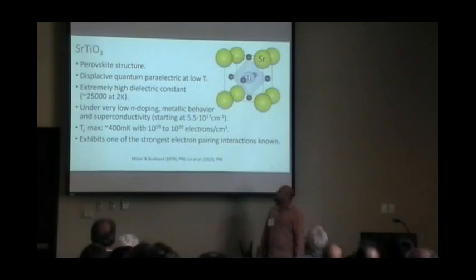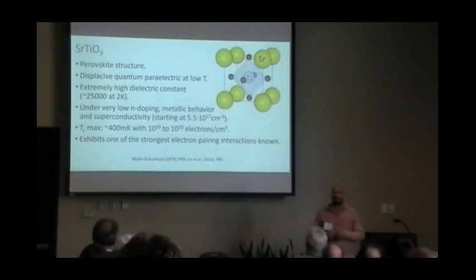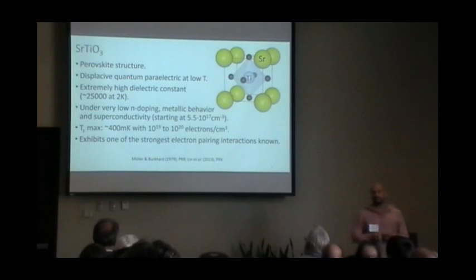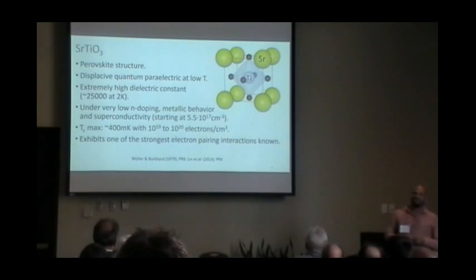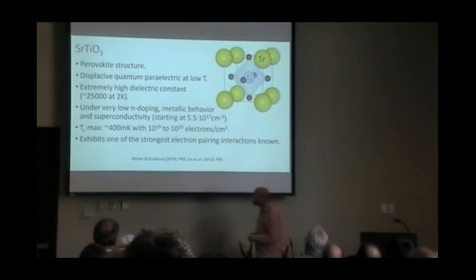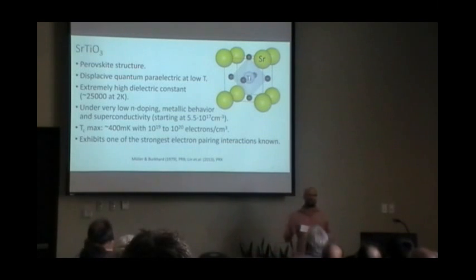Yeah. So strontium titanate is a perovskite, and it actually has a very long history. It's a very famous material. One of the reasons is that it's an incipient quantum ferroelectric at low temperatures, and you don't find that very often. It has an extremely high dielectric constant of 25,000, and the dielectric constant is proportional to the Bohr radius of the dopants that you put in.